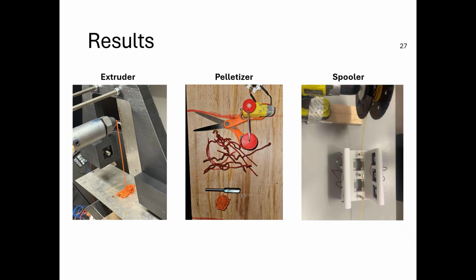Our cutter, however, had many issues. Originally, we planned to cut the filament using a rotating two-blade router bit with a 1/4-inch shank to have more consistent cuts with a constant speed. But testing showed that the filament was sticking to it and rotating with the blade as opposed to being cut by it. In an attempt to resolve that issue, we were looking at changing the speed, but then later decided to completely switch directions as we wanted to have cleaner cuts using a horizontal cutting approach.